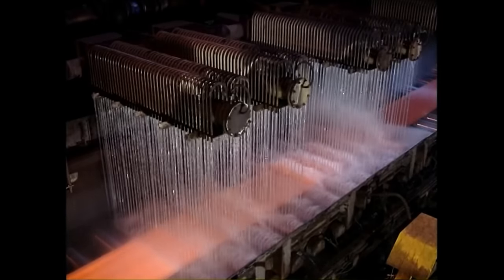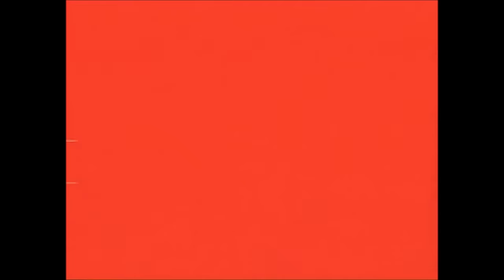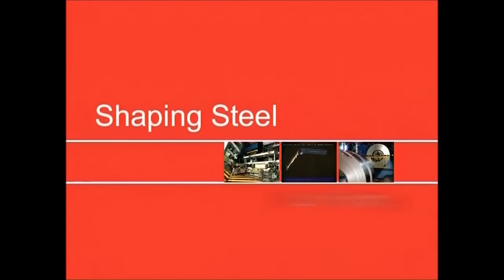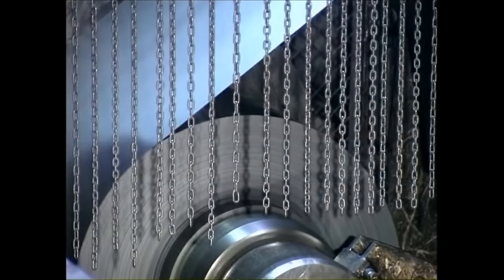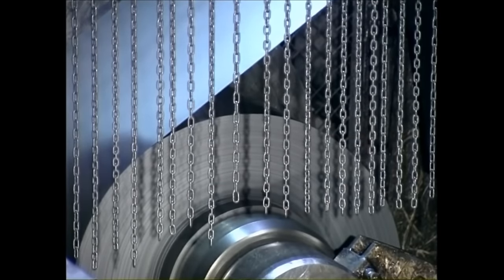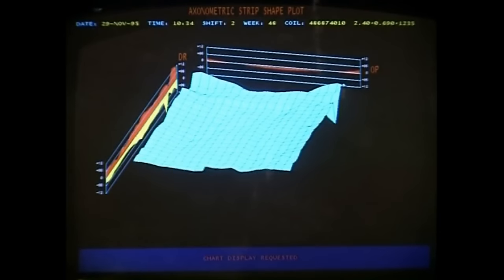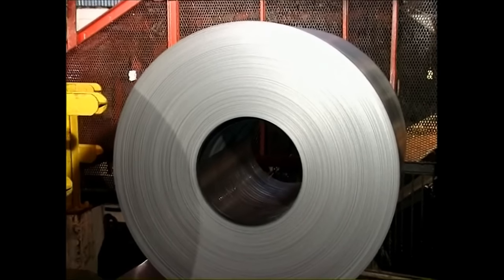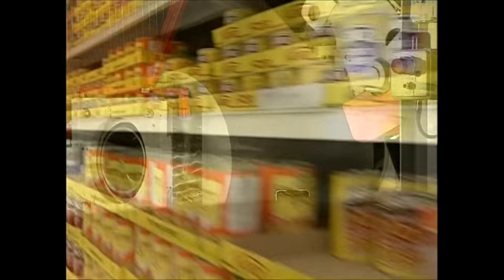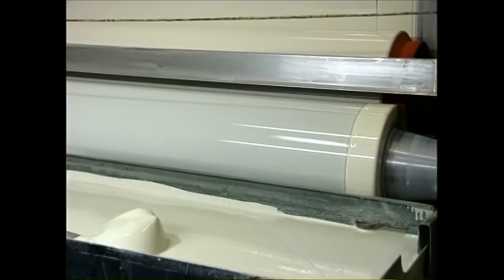The rolled steel is then cooled in a way appropriate to its end use, and prepared for further processing or dispatch. One of the further processes is cold rolling of strip. This is used to produce a thinner, flatter product than is possible on a hot mill, down to a thickness of 0.15 millimetres. Forming properties and surface finish of cold rolled strip is better. It can also be coated with zinc to protect it from corrosion, with tin for cans, and with a plastic coating or paint for protection and decorative purposes.